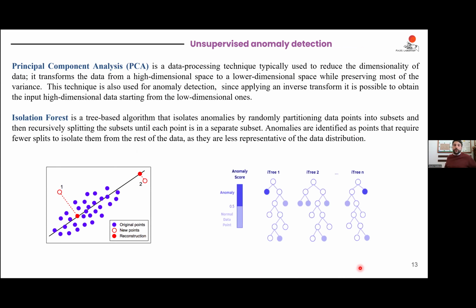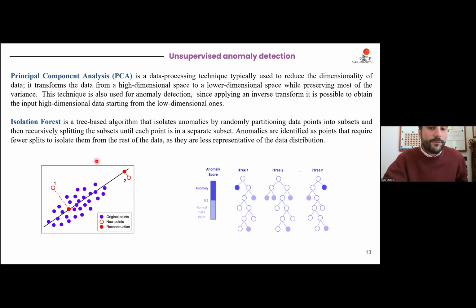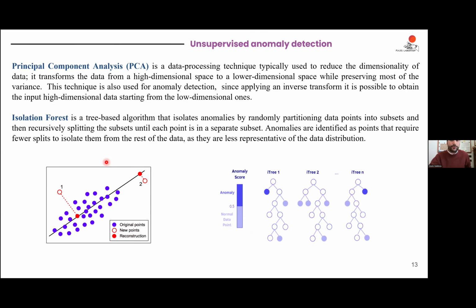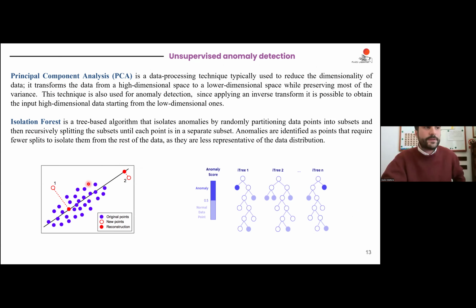Indeed, machine learning algorithms open the pathway for a more complex, multivariate way to look at the data. In this case, you can have a reconstruction-based algorithm in which you use principal component analysis to transform your good deposition data into a low-dimensional space. And once you learn the linear transformation that allows you to do it, you can use the inverse transformation to reconstruct the data. If the data are the same that you used to develop this weight matrix, this linear transformation, the reconstruction error is zero. Otherwise, if any deviation happens, the reconstruction error, when you encode and then decode the data, is going to be really high.